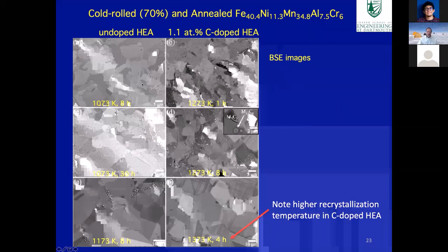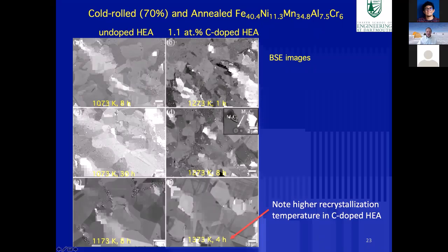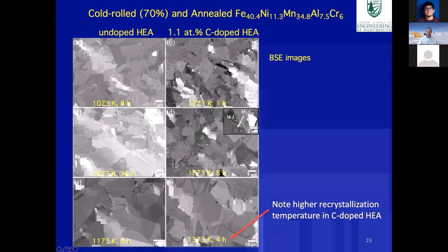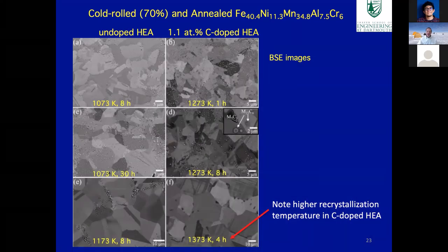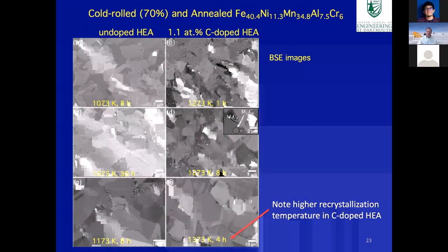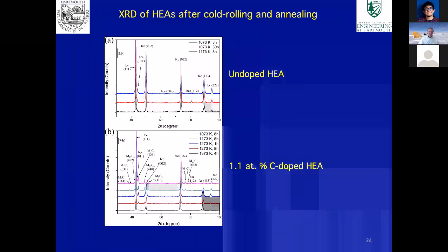One is you can see that there's actually a number of precipitates that are formed in the alloys, and they look different at different temperatures. The other is that the annealing conditions for the carbon-doped alloy were higher than for the undoped alloy. We annealed at high temperature because recrystallizing the carbon-doped alloy required those higher temperatures, which is what you might expect if you had some solute drag like that.